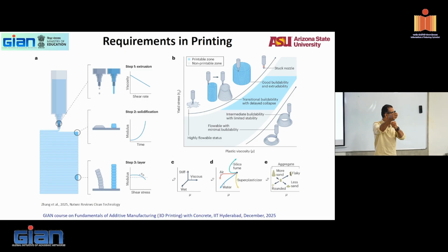Removing the contacts between particles, because it is the particle contacts that create shear stresses. This movement between particles is restricted by those contacts, correct? So if I start to break the contacts, if I start to move particle contacts away, which means automatically lowering the yield stress. Everybody good with that? So I want to get to a point where I break the bond between particles.